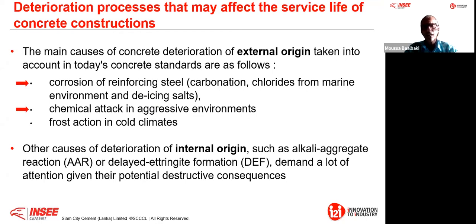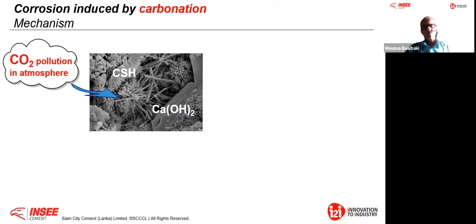Again, here, if I look at corrosion due to carbonation, for example. If I take, for example, a microstructure of concrete, as I told you, you will have calcium silicate hydrate, and if you do not use Portland composite cement or aluminum silicate material like slag, fly ash, whatever you put in your blended hydraulic cement or your Portland limestone cement, you have plenty of Portlandite.